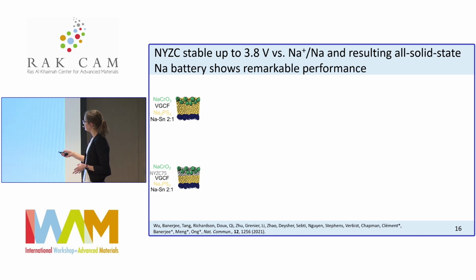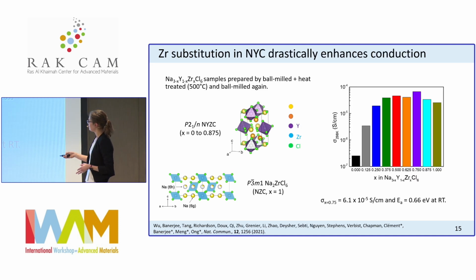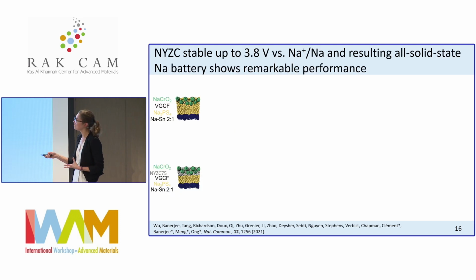So what that means is that if you have a low conductivity, but you have a material that's very stable against a cathode, you might use it as a catholyte. So it's kind of a coating that you would put on the cathode side, where you'd be using a better solid electrolyte, so a solid electrolyte with a higher sodium conduction, on the anode side. And so most of your sodium is transported by your solid electrolyte, and then you have a thin layer of this catholyte just to protect the cathode.